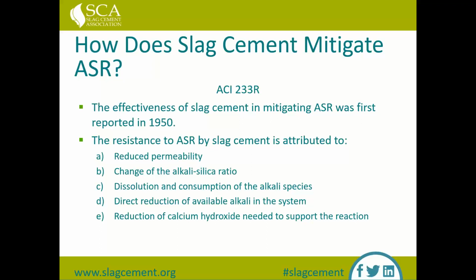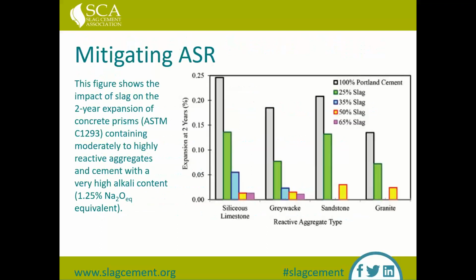And the last factor listed is a reduction in the calcium hydroxide, and the calcium hydroxide kind of supports the ASR reaction, so it's helpful to reduce the calcium hydroxide. And that's also a big part of the reduced permeability, is the reduced calcium hydroxide associated with systems with both Portland cement and slag.